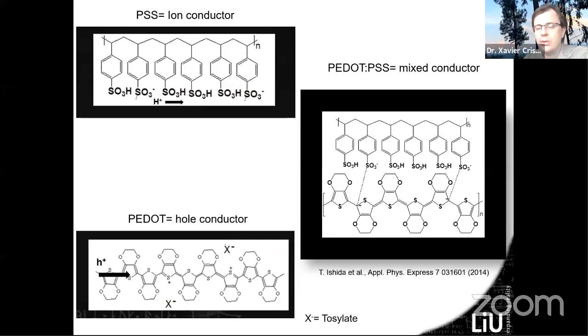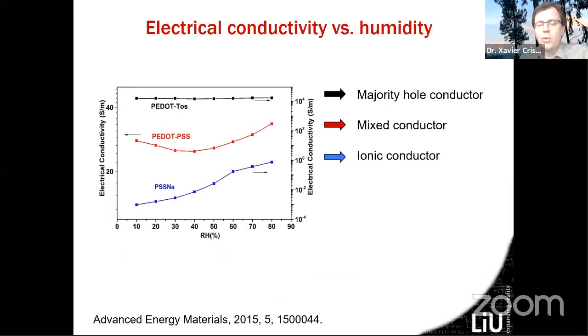So we can look a little bit at what happens to them when we expose them to humidity. When you expose to humidity, actually not much is happening for the electronic conductor. For instance, the top one, PEDOT-Tosylate, there's not much happening. Now for the ionic conductor, the PSS there, we see that when you increase the humidity, basically the ionic conductivity increases by almost 3 orders of magnitude.